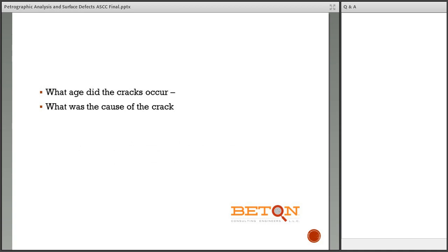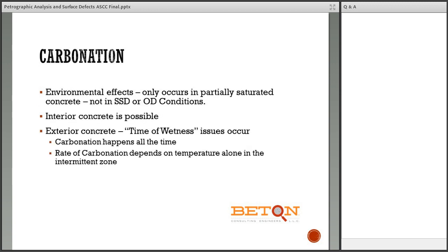Some things you may or may not be able to answer. What age did the cracks occur? Because carbonation, as we're about to find out, proceeds at a known rate until it doesn't proceed anymore. And further, what was the cause of the crack? Frequently, the cause of the crack sits outside of that 4-inch or 3.5-inch diameter core. Perfect example, carbonation, which Mark's going to talk about how we diagnose it. It is an environmental effect.